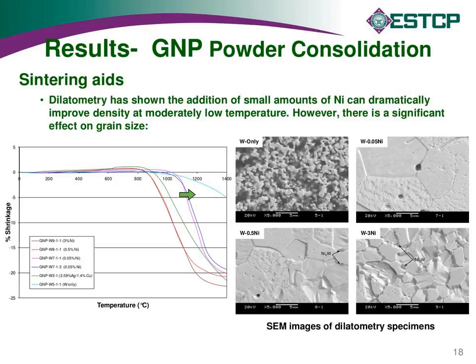If you look on that graph, there's a series of sintering aids, and you'll notice that the more nickel we added, the higher the sinterability. The two lines on the left, where we got a lot of shrinkage at very low temperatures, were 3 and 0.5 weight percent nickel. Then we added lesser nickel, and then we tried some combinations of silver and copper, because nickel causes some coarsening of the tungsten. So we tried some silver copper additions too, to try to keep the actual grain size down. So this was the sintering aid diagram and how they went.